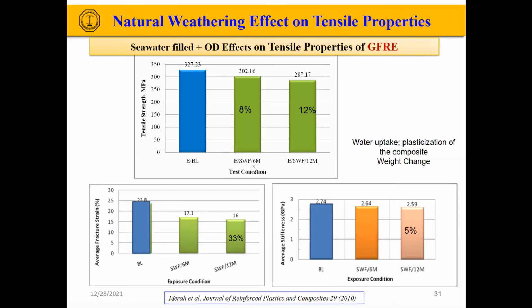But after 6 months of seawater filled and outdoor exposure, the tensile strength reduces by 8%. After 12 months, it reduced by 12%. As you can see, this is different from vinyl ester pipes, where the strength increased because it was cured. And here also maybe because epoxy is more hydrophilic, the water uptake, moisture uptake, plasticizes it and reduces its strength.